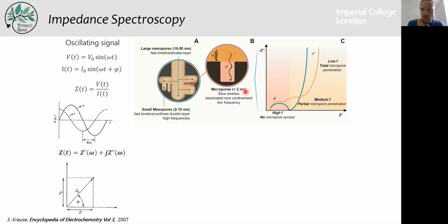And here is a little scheme of a typical hierarchical carbon, where we have large mesopores, smaller mesopores, and then small micropores. And we can see that when the frequency is really high, we have no penetration of the ions inside the micropores, because they are basically going from the counter to the working electrode very, very fast, and they don't have time to penetrate. So the highest capacitance and the highest accessible surface area will be available only at low frequency.